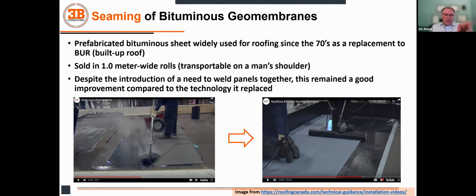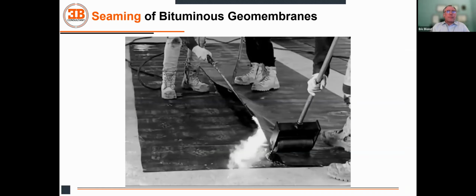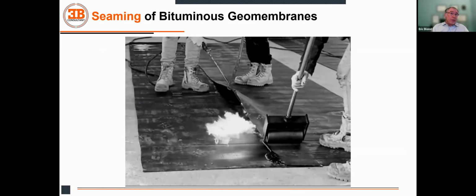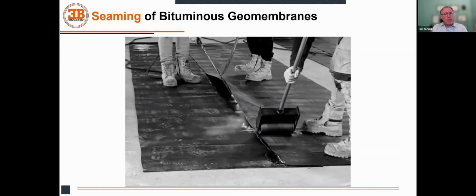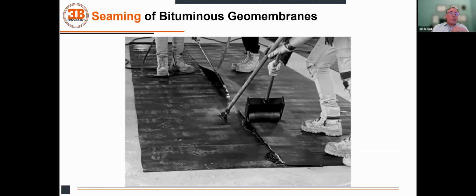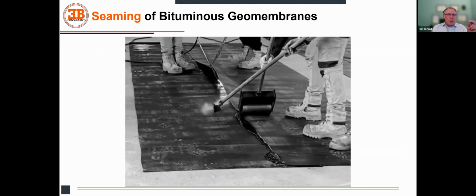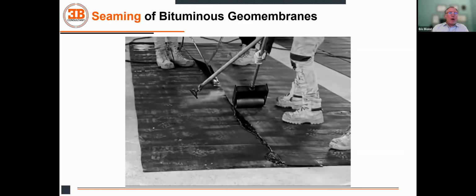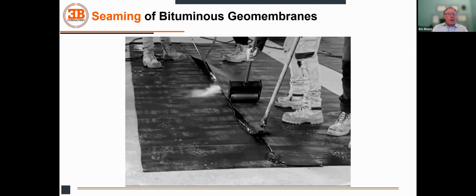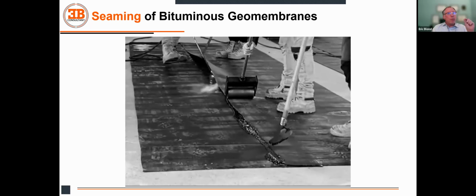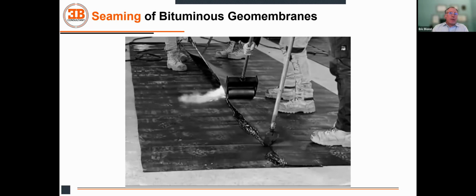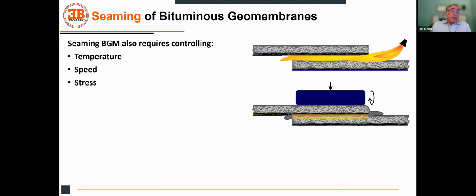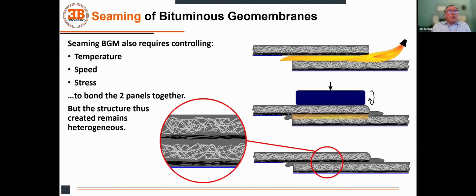We have to understand that despite the very high number of welds, because we have basically one seam for each square meter of material or more, because of the width of the rolls, this is working well. This technology, which was used for roofing, was extended to geomembranes. And this is an example of a bituminous geomembrane being welded. You can see again the temperature being controlled, the speed being controlled somehow, and the pressure being controlled. The three parameters are always of importance. You must control all three of them to get a good assembly. Voilà. Again, it's the same thing. We apply some pressure and we bond the panels together.